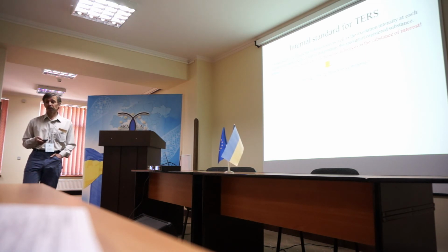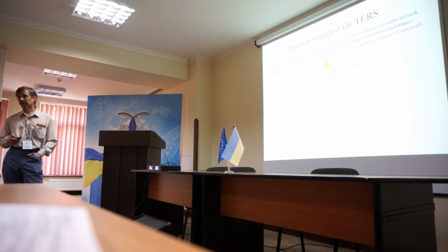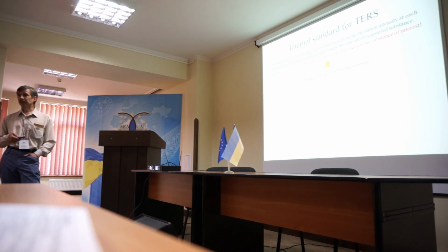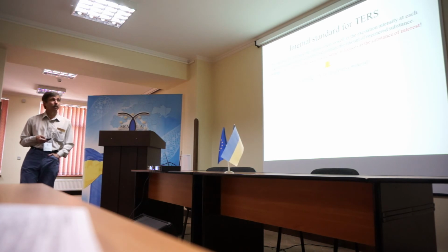So we can use some reference material, but maybe the most elegant idea, as it seems to me, is just to bring this material to the point of our measurements on the tip. In this case, we are guaranteed that we have the same amount of molecules, a constant amount of reference material, and it's deposited in the same manner on the surface of our tip, if it's chemisorbed molecules, and we can follow the Raman signal from this coverage to make some conclusions about the local enhancement.